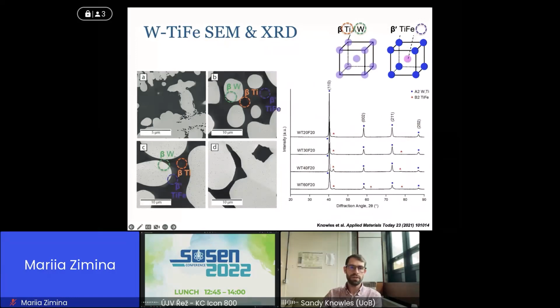BCC tungsten, which will have some amount of titanium and iron dissolved within the BCC. And then we get this beta prime titanium iron phase in purple. What was interesting, and we were aware of, but didn't know if we would see it, is that there's also a second or third phase of BCC, which is BCC titanium. So as well as having this two-phase precipitation gap between having the beta prime, there's also a spinodal reaction as well. So you actually have a three-phase structure. So two BCC phases and then this beta prime titanium iron.